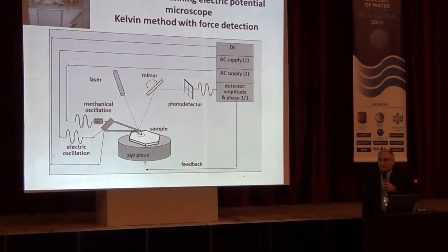We entered this topic by the small end, when we started using Kelvin force microscope, which is just a modification of the atomic force microscope, in which case the tip of the AFM is used as an oscillating Kelvin electrode that allows us to measure potential along any surface, including insulators, without contact.